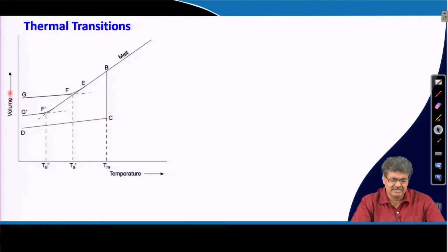So, if we graphically represent the volume versus temperature curve, if we start from a molten state and decrease temperature, the volume decreases, and if the material can pack well and crystallize, then volume suddenly drops and a solid state is formed at the melting point or melting temperature, and when we decrease further, the volume change is negligibly small because it is in a solid state now.